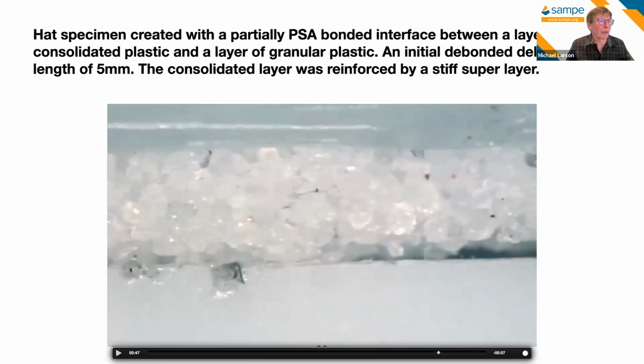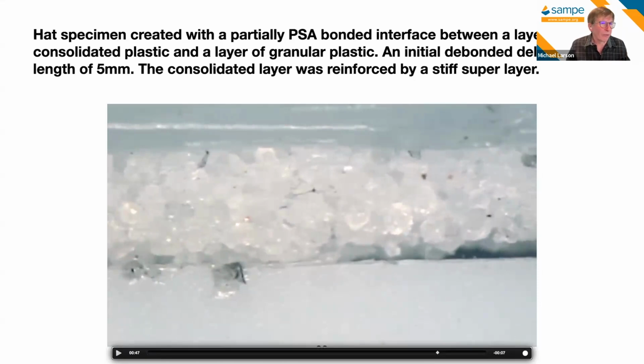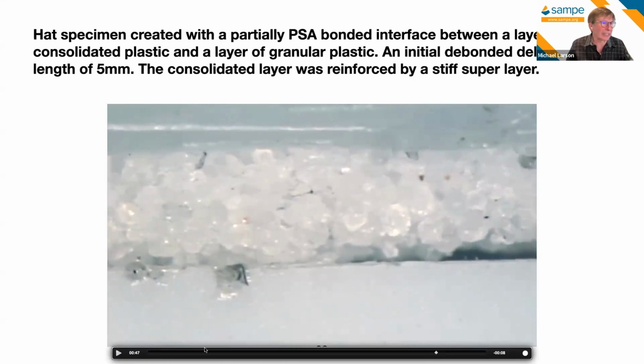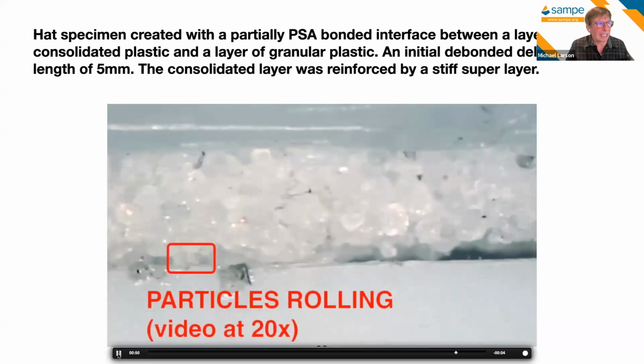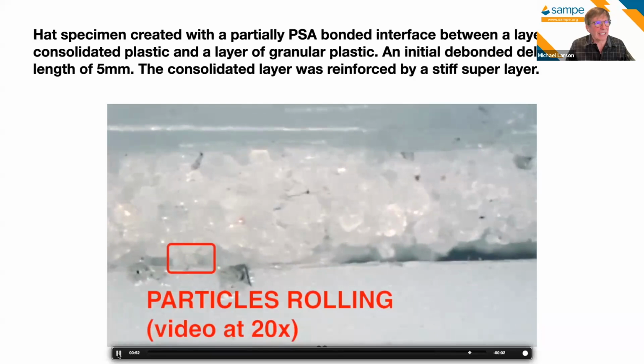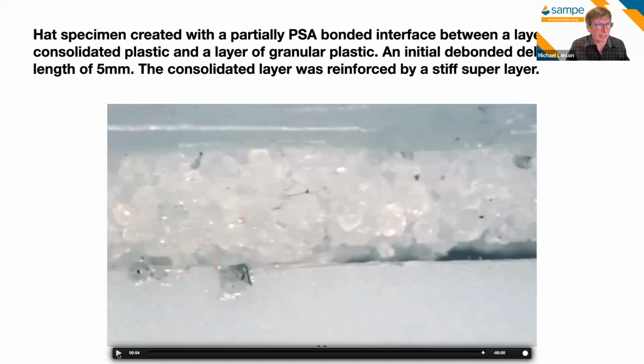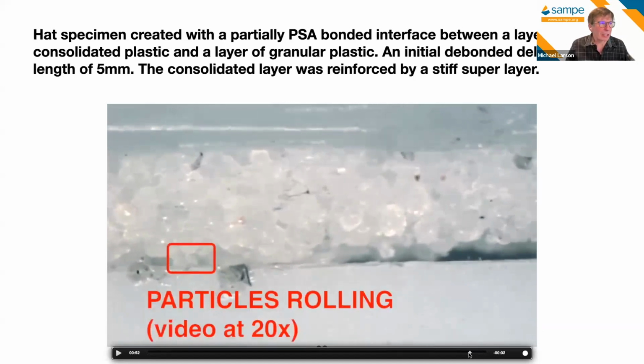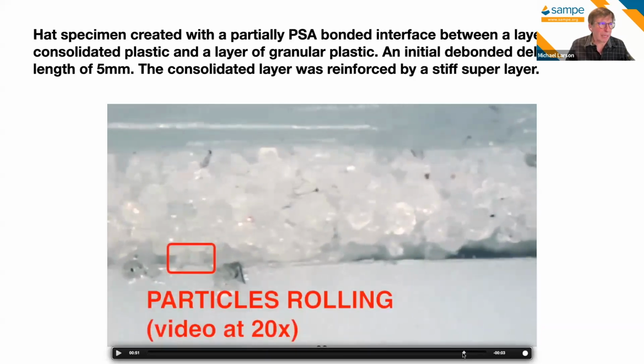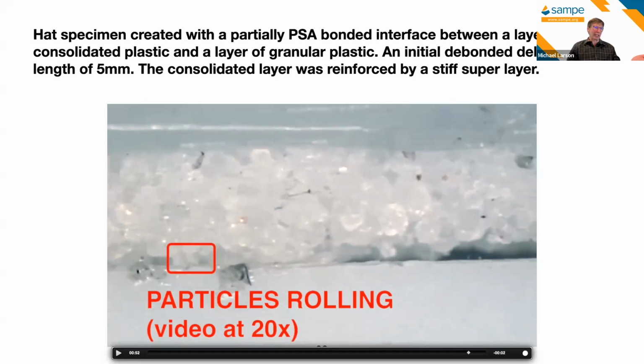So to stress the fact, what follows is scrubbing the video forward and back at a high rate. You see there is a lot of deformation that gets induced between the substrate through our PSA without the PSA letting loose, as we say. But as that red box showed, there was an interesting failure that ensued that wasn't expected, of the particles making up the material actually rolling along the interface.